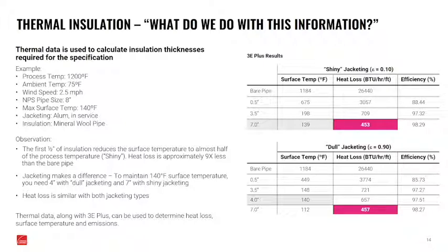or stainless. So we look at the bare pipe surface temperature on the top table. You'll see we have just a little below 1200 degrees Fahrenheit. So you have a little bit of heat loss through that wall, but metal conducts heat quite readily. Your heat losses are on the order of 26,000 BTUs per hour per foot length of pipe. And remember, this is an 8-inch pipe.